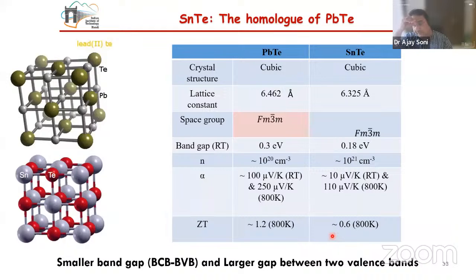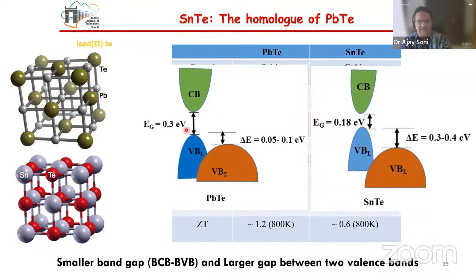Okay, but if you can tap into the control of the valence band, two valence bands exist in both of these materials. You can see here that the band gap for PbTe is large, while the gap between the heavy and light valence bands is small. While in SnTe, the band gap from the bottom of the conduction band to the top of the valence band is small, while the gap between the light valence band and the heavy valence band is large here. Okay, so if you can tap into these two valence bands together, then you can perhaps have a large effective mass. So what I'm saying here is that you can compare.